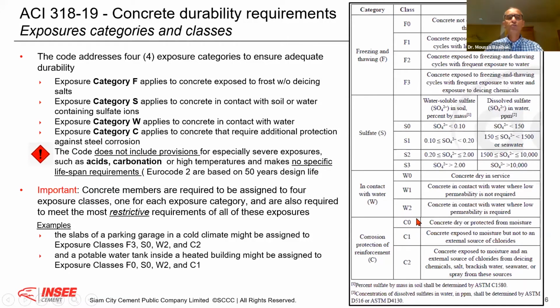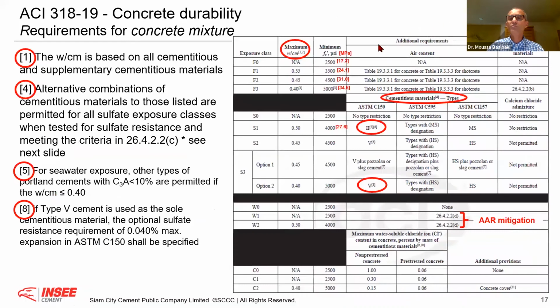Therefore, you will see they also have limiting values, exactly like in the EN. What they don't have is a restriction on the cement content. In the European standard, you have the minimum cement content, the maximum water cement ratio and the minimum compressive strength. In the ACI, they put requirements only on the maximum water cement ratio and the minimum strength. They don't put a restriction on the minimum cement content. That is really the big difference.